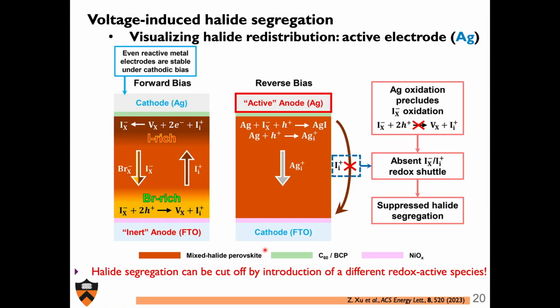Okay, so here's the situation. When my silver is a cathode, it's just the same. I have anodic and cathodic reactions that involve iodide. But when I have silver as an anode, now instead of iodide getting oxidized, it's silver that gets oxidized. And I end up creating all of these silver interstitials, and that's what is sort of taking over when I oxidize the system.